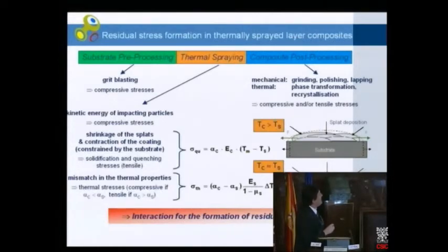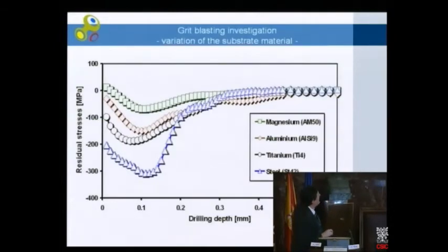I will not go into too much detail, but we should not forget that any type of post-processing, especially mechanical post-processing, as we need it for precision grinding, polishing, machining, will also be distinctly affected by the contributions of the earlier process steps to the total stress situation in our layer composites. And I will show you that with a simple example. It is the same geometry of a material that is coated, and it is the same type of coating. We will just vary the substrate. Magnesium, aluminum, titanium, and steel.